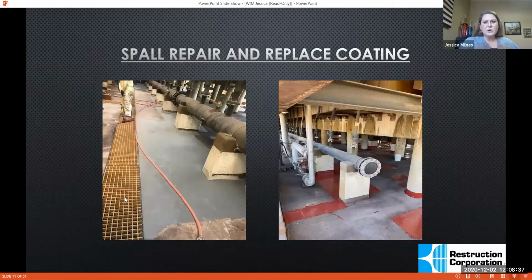So the next step after we've removed the coating, and we've taken out any of the concrete that is delaminated or disintegrated in some way, shape, or form, is we put down new concrete, and you can see the sharp edges. The goal here is not to remove and replace everything. The goal is to only remove and replace what is delaminated or what is no good. So that is why it's patchy as opposed to just removing the entire floor. And we'll cover why we do some of that. Then we come back in with a coating over the top of it.